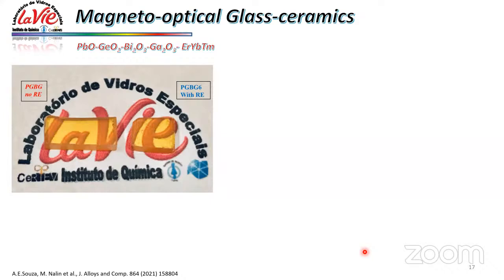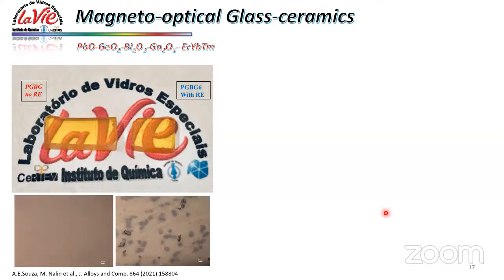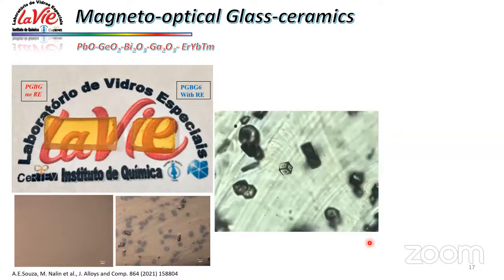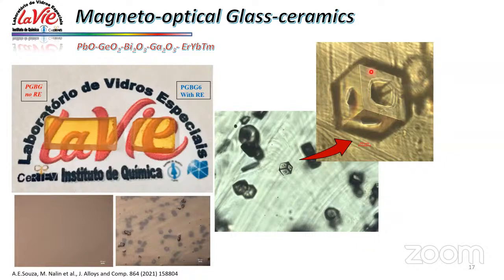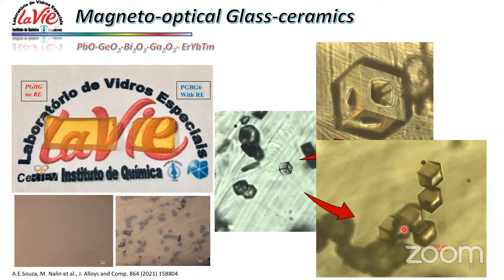So thinking about getting magnetic glass ceramics, some years ago we studied this multi-component glass system here containing lead, germanium, bismuth, gallium, and it was doped with several rare earths. At that time, we were intending to obtain white light emission, but we had some surprises concerning this glass. So you observe that when we put some rare earths, the glass crystallizes, and it crystallizes with this kind of glass ceramic phase. It's a cubic one, very nice crystals.